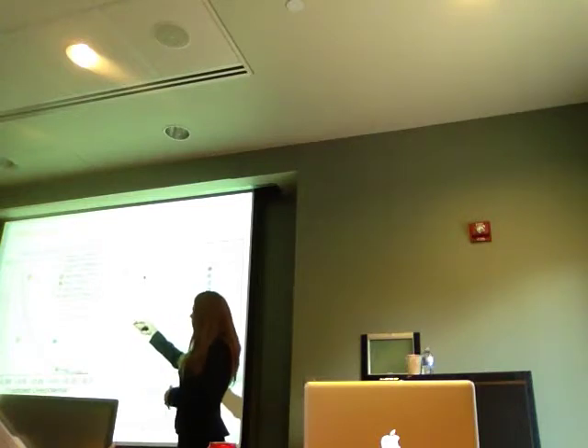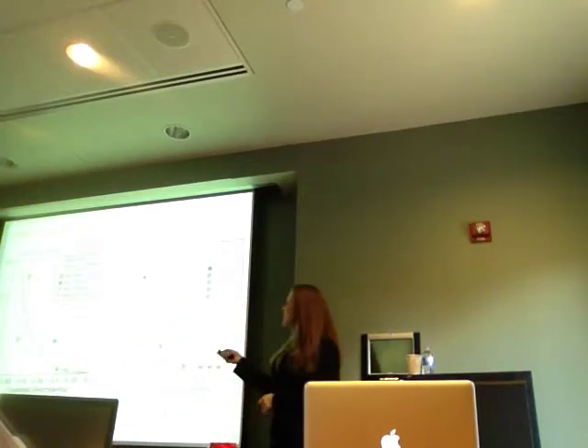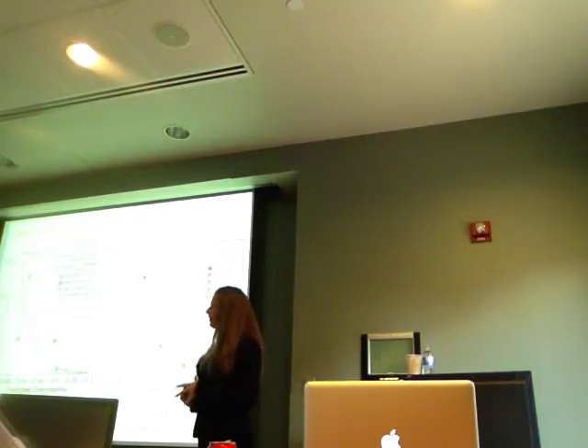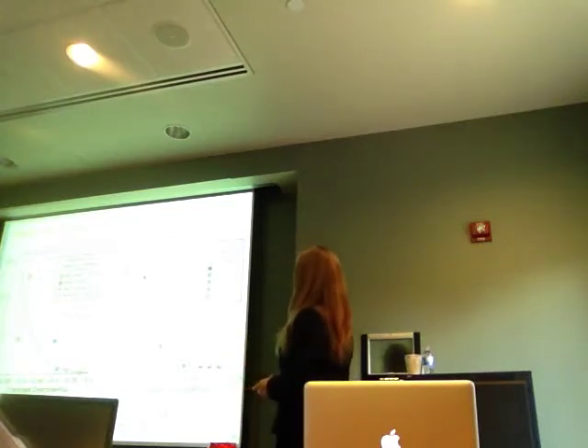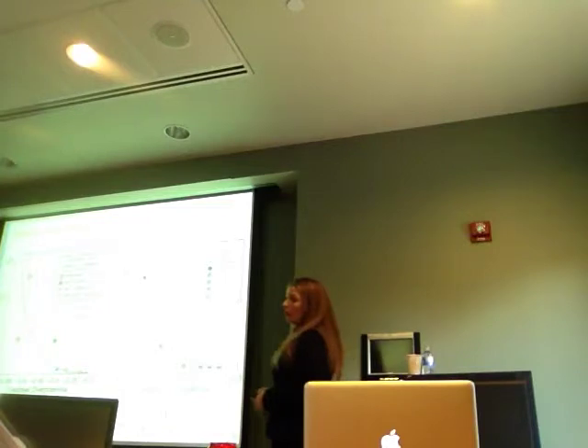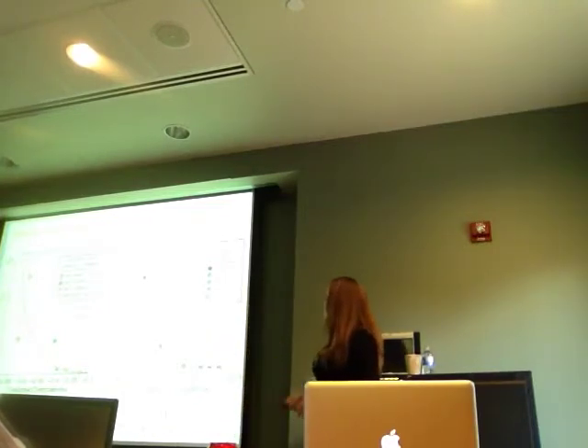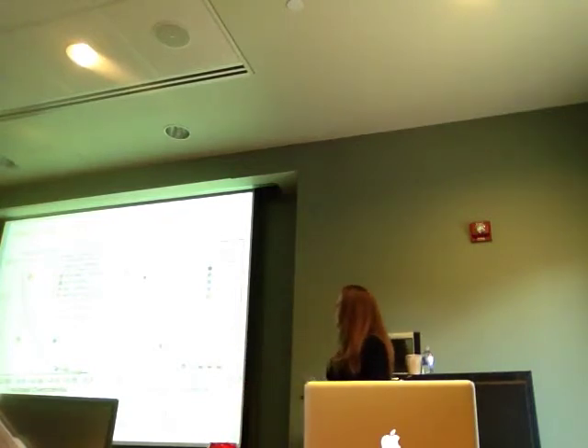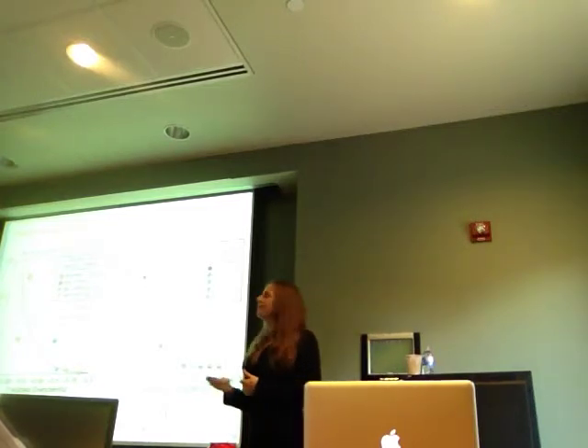We have an exponential decay as long as we're assuming that the hydrogen diffusivity is 10 to the negative 10 and our critical diffusion or critical fracture distance is 0.9 microns. I did the same thing with all of our sensitized data in sodium chloride polarized. And again, as your concentration of hydrogen decreases, the magnitude of your predicted overpotential decreases. Nice exponential function, as long as our hydrogen diffusivity is 10 to the negative 7, and our X crit is 0.9 microns.